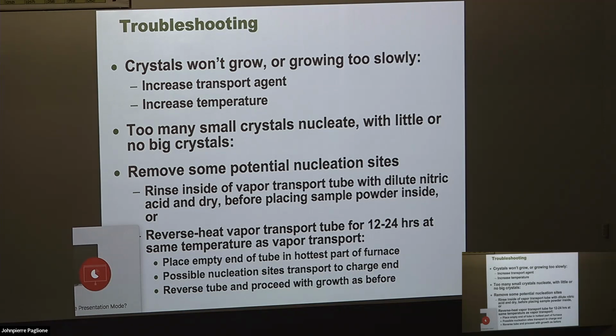And then there are various things that can happen that you don't want to happen. So if the crystals are growing slowly, you can add more transport agent or maybe increase the temperature. You can try to clean the inside of the tube with nitric acid. Maybe reduce the number of nucleation sites. Sometimes reverse heating: in other words, you change the direction of the gradient for a while and then you reverse it to the direction you want. Sometimes that helps too.